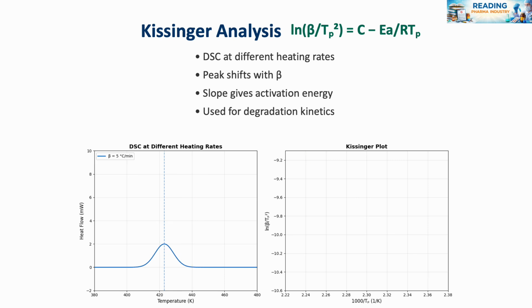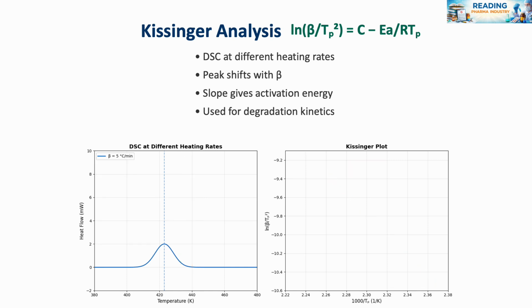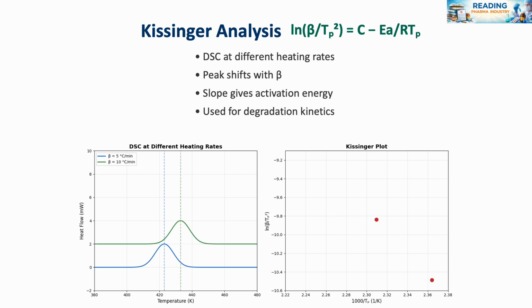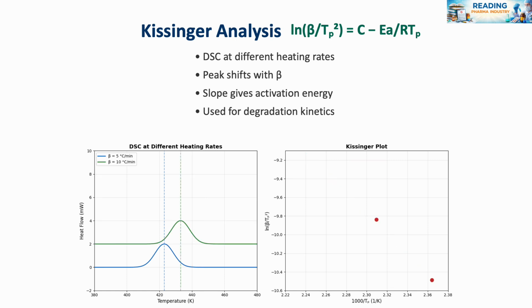As the drug is heated, there will of course be a chemical decomposition, and that appears as a peak in the DSC. In many cases it comes out endothermic because it will break bonds, because of dehydration, decarboxylation, or because volatile components are released. The way this works, as you can see in the plot, is the DSC is used to run a sample at different heating rates, in this example from 5 to 20 degrees per minute, and you record the peak temperature.